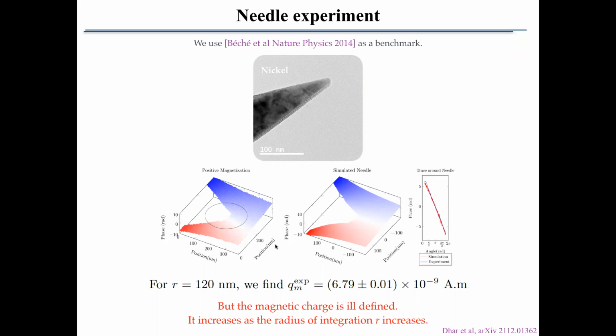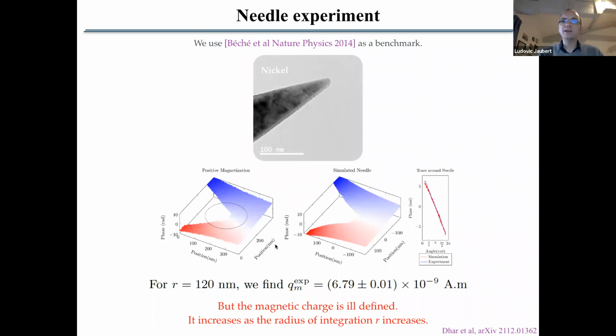But so what's the domain effect? I mean, the nickel is a ferromagnet, right? But ferromagnet is sort of soft, right? There's many domains, right? How does that play a role in this? So in this case, what you do is that you magnetize the sample beforehand. So you really put it in a strong magnetic field, just to be sure that it's really magnetized. And if you're at low enough temperature, it will stay in this magnetized state for long enough to do the experiments. I see. Thank you.